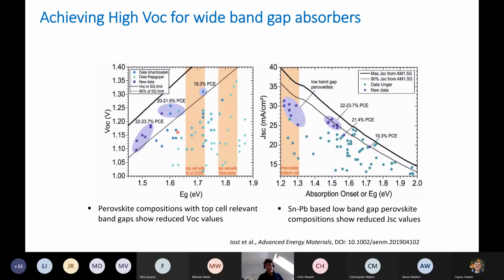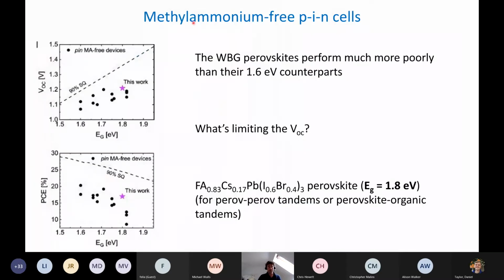Once more, most of this data is originating when an organic ion called methylammonium is used in the perovskite absorber. But this methylammonium ion is actually very unstable. It's thermally unstable, and if we substitute it for formamidinium, we get much higher stability. But if we show this data of the open circuit voltage for cells without methylammonium, it becomes even more challenging to get high voltages as we go to wider band gaps.